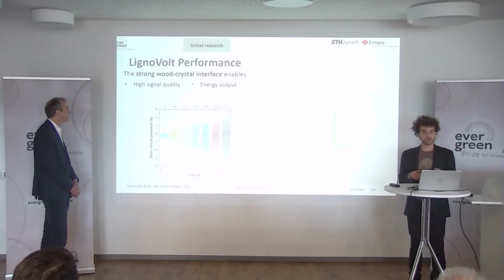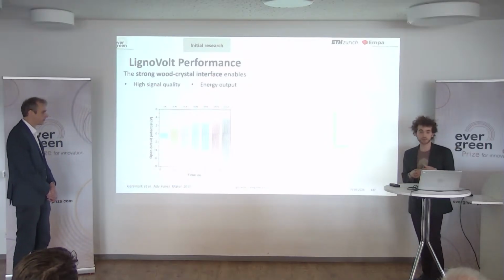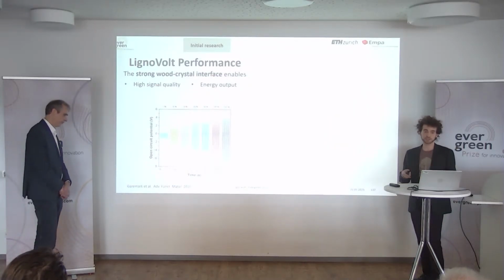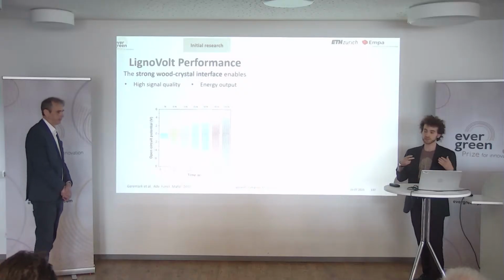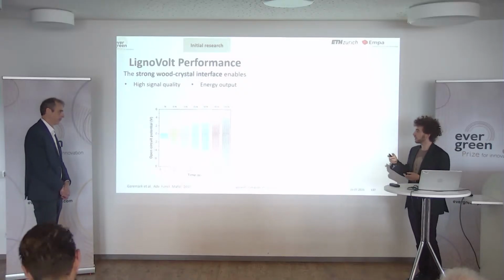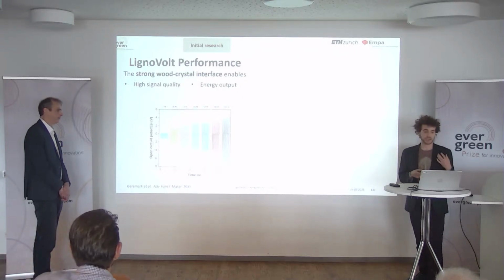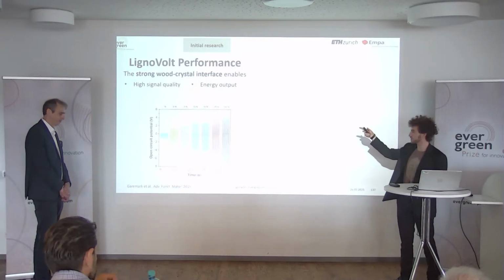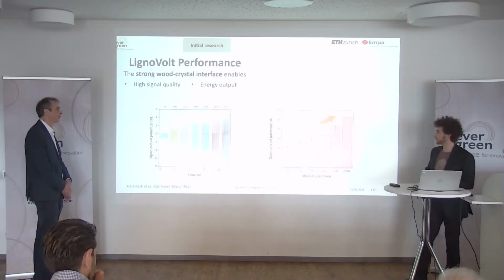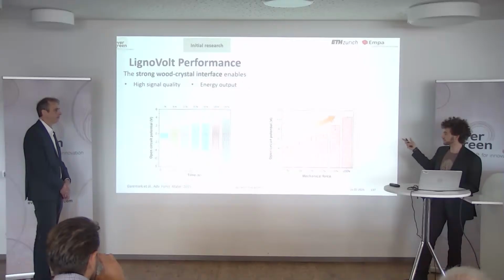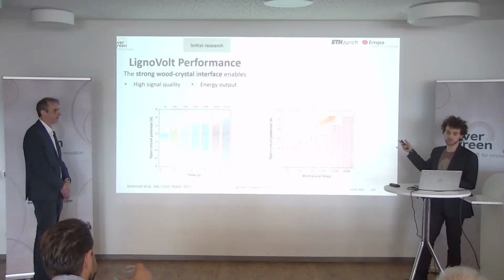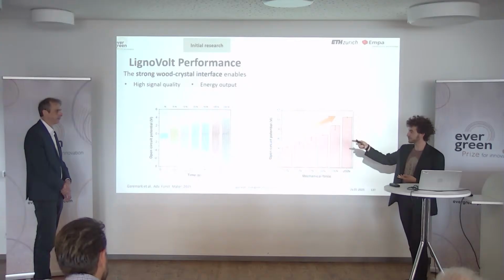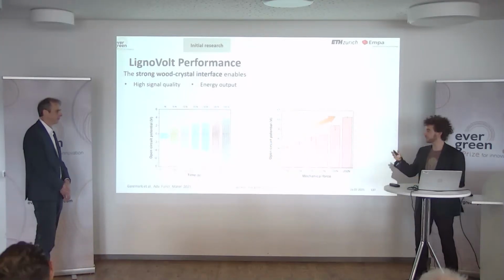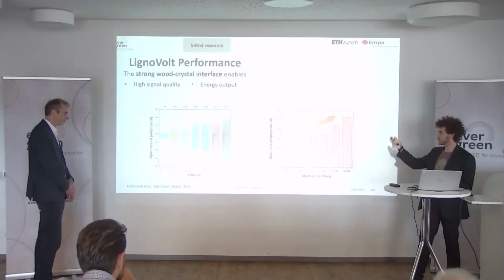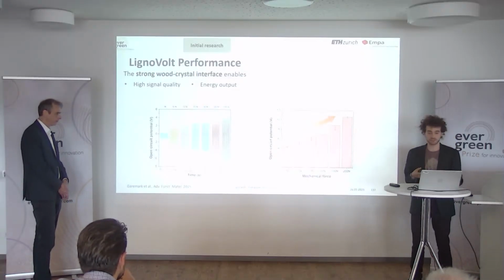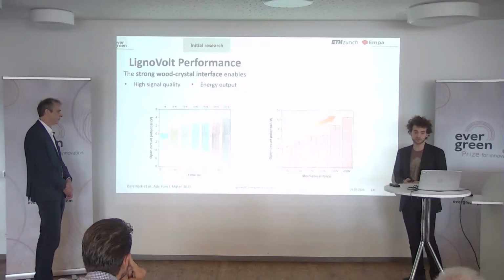And what we were most interested to look at is how our performance evaluates with different strengths, because that will be key to know how we overcame the brittleness of our Rochelle salt. So the strong crystal interface enabled a very good signal quality and high voltage performance at high forces. When we increase the force, we can see that the voltage output scaled almost linearly. And when we do repeated taps, we can see, and we also showed in the journal, that we obtain very constant results, and hence we have a very good signal quality. And once again, this is from completely natural products. But how can we see this?